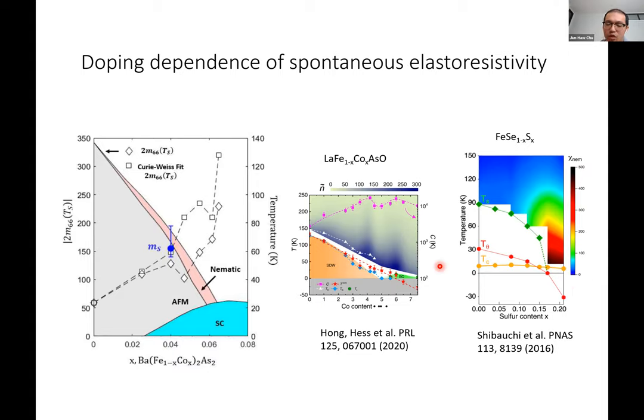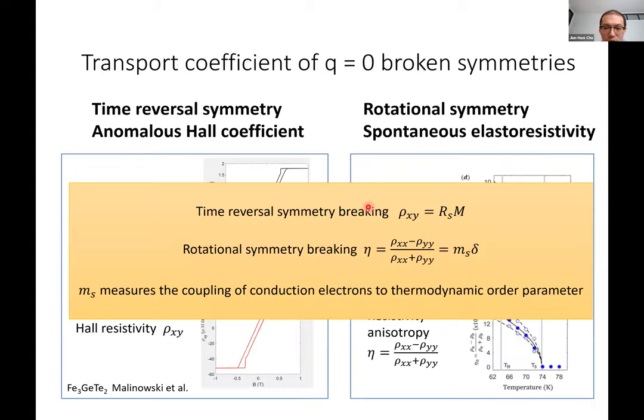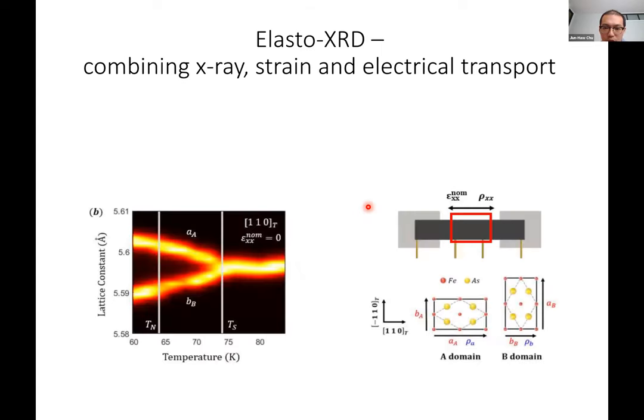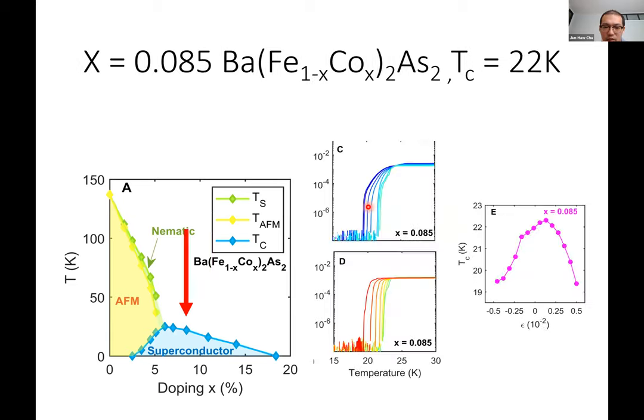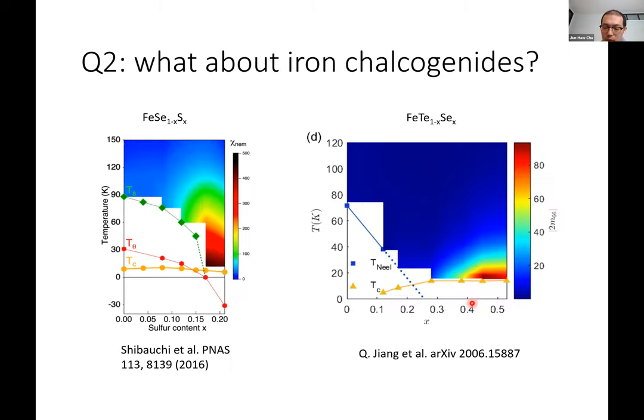And also the other side, which is by tellurium doping. We have measured a tellurium doping that I think can be considered as the overdoped side. So we have measured somewhere here. Here, iron selenide is somewhere here, right? And iron selenide corresponds to x equal to 1 here. And then the nematic phase is being suppressed along this direction. So this is basically the overdoped side of the nematic quantum critical point. And we also didn't see a very strong suppression. I mean, there is suppression. You can clearly see this change of the Tc. But it's definitely not as strong as at optimal doping or the underdoped side of cobalt-doped 122.